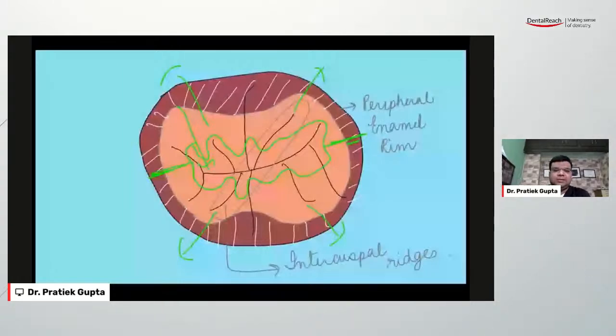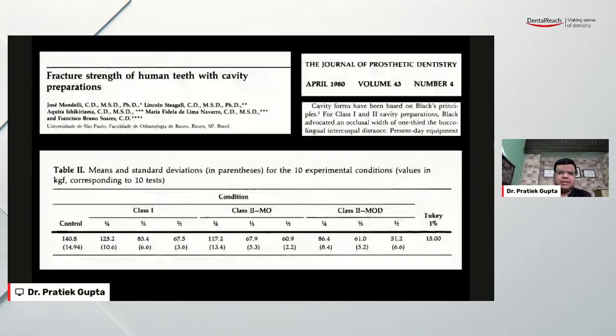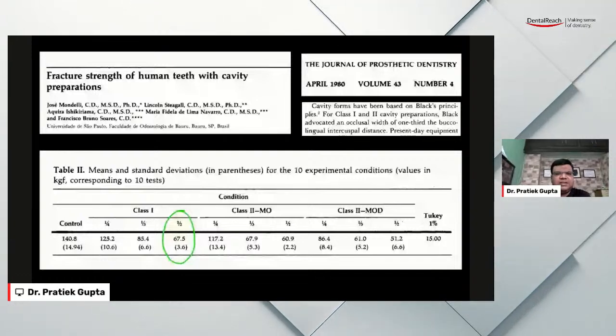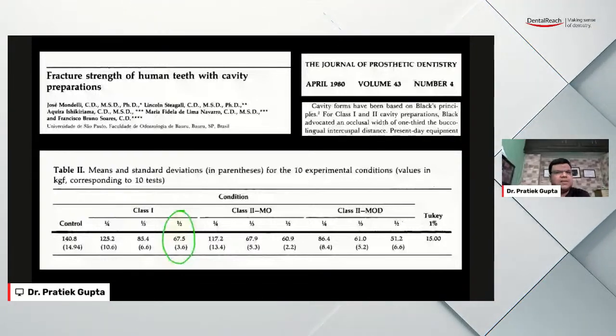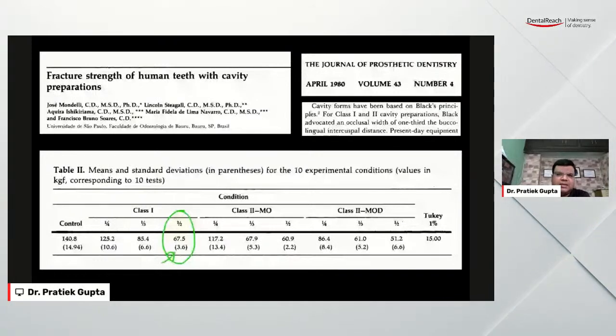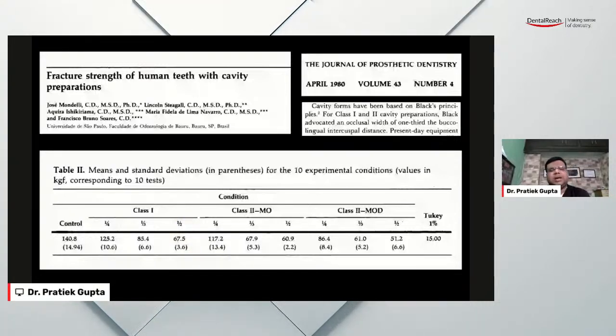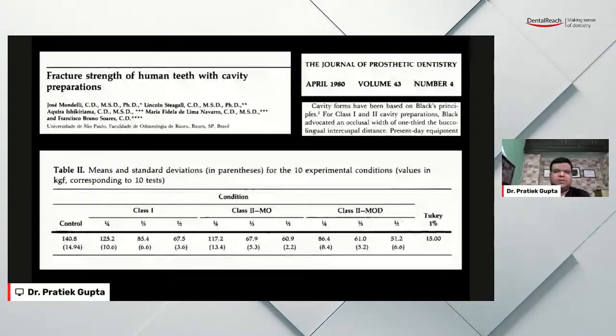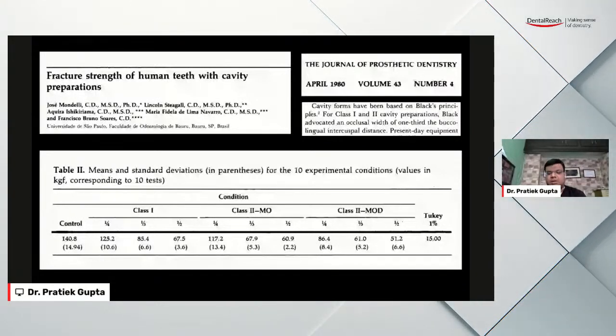But that was the biggest flaw with amalgam. Studies suggest that if you just take off half the intercuspal distance, you see so much tooth structure loss. Just a class 1 with half the intercuspal distance. So extension for prevention did not prevent anything. It just made it easier to progress from one stage to the other. What do I mean? From a class 1 to a class 2 to an MOD to a root canal treated tooth to finally into the deathbed and having an implant in place.